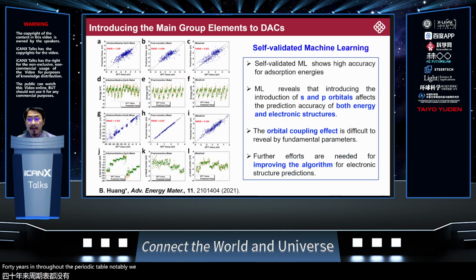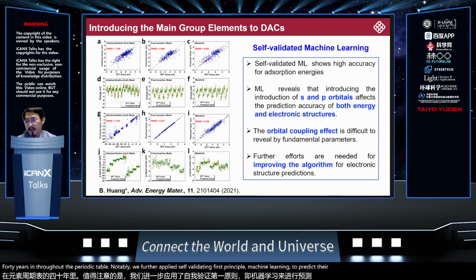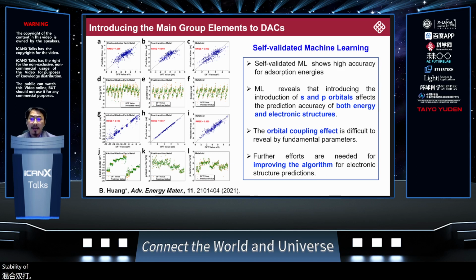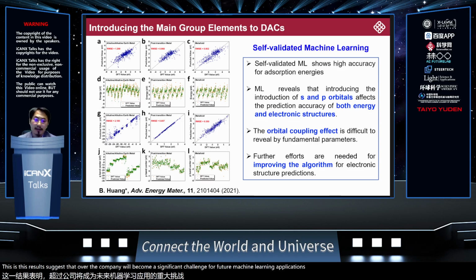Notably, we further apply self-validated first principle machine learning to predict their performances. The thermodynamic stability of a dual atomic catalyst can be predicted with a relatively high accuracy. In contrast, the p-band center predictions show much lower accuracy. This is due to the evident electronic modulation induced by strong p-p coupling acting as noise signals. These results suggest that orbital coupling will become a significant challenge for future machine learning predictions on electronic structures.